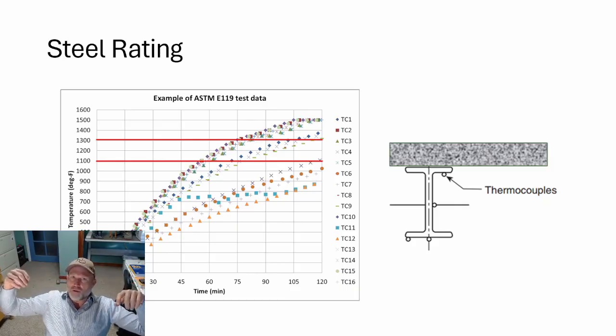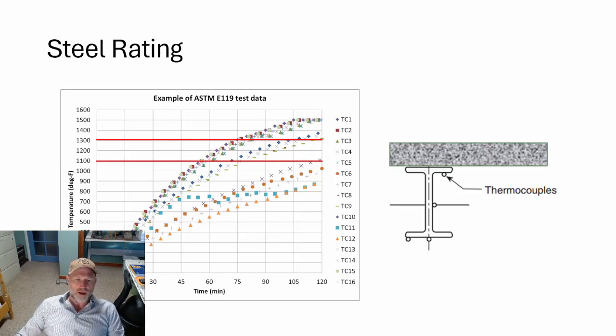That's one factor. The other factor is applied load bending a weakened steel member. But a lot of people don't recognize that the thermal expansion on the bottom is greater than at the top, and that creates a smiley face profile. So here, the bottom member is profiled by this series of thermocouple results. It's hotter than up high. Now, if you look at 60 minutes, this is an analysis for 60-minute applied fire-rated material. At 60 minutes, 1100 degrees Fahrenheit is the target for failure, about 538, thereabouts 550 degrees Celsius.